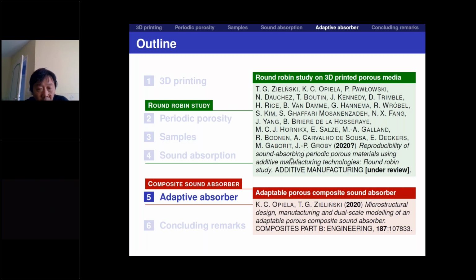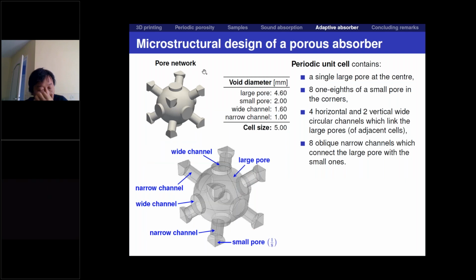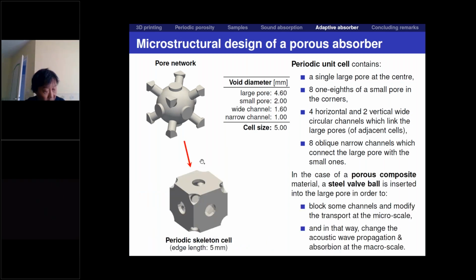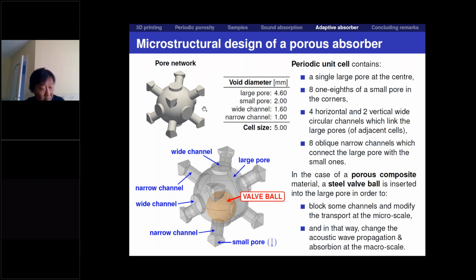Yeah. So I will briefly show you some results for the second research activity. This is an adaptable porous composite sound absorber. I proposed a kind of pore network. This is the voids, so we will print obviously the solid part of it, the solid skeleton. The idea here is that we have a periodic unit cell with a large pore inside. It is connected with thick channels and smaller channels, which are skewed, and there are some smaller pores, but maybe the main point is that we have a valve ball inside, and this is made of metal. So you will see that we will use additive manufacturing technology, but in a very specific way.